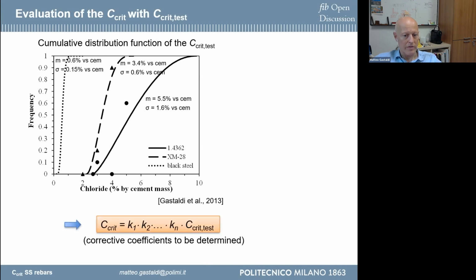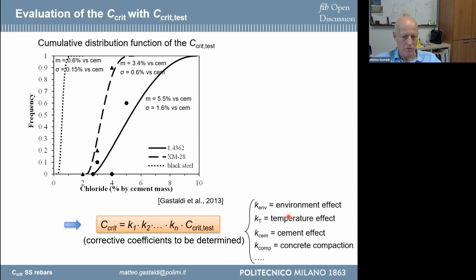Naturally, if you want to have the result related to the real critical chloride threshold, you need to have information about the coefficient that helps you to obtain this parameter, considering the result that you obtain in the critical chloride threshold related to the test. And so you need to have information about the effects related to the environment, the temperature, the cement type, the compaction, and so on.